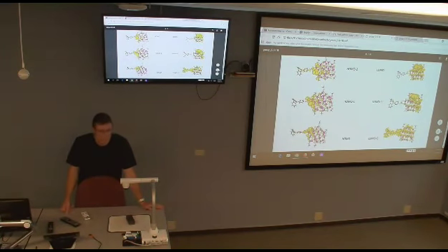Okay, so hypothetically, suppose we found HOMO is localized on the dye, and maybe HOMO-10 or HOMO-12 is localized on the quantum dot, and that state is optically active. In that case, it would be more favorable for hole transfer from the quantum dot to the dye. Again, the coupling and really how quickly it will be occurring to this state, we don't know. It depends, you need really to calculate it and see, right?